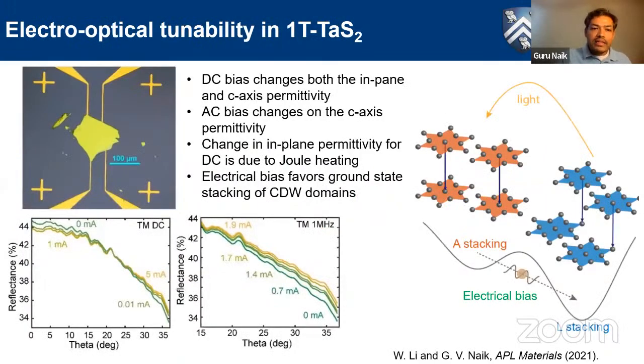Okay, so not just in the case of light, but we can also see this tunability with an electrical bias. We simply apply an in-plane DC bias. So here is our tantalum disulfide film, and then we have gold contacts which are underneath this film. And there are 4 contacts here, and we apply bias across 2 of them and measure current through the other 2. And what we see is, as we increase the bias current, from 0.01 milliamp for this green curve to about 1 milliamp for the red curve, this is for the DC case, we do see that the angle resolved reflectance shows a change. And similarly with the AC bias at 1 megahertz, we do see a similar change in reflectance. And this is quite a lot of change in reflectance for this 20 nanometer thin film.